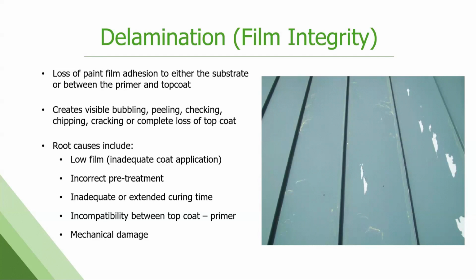I've listed the most common ones we see, which is low film. That's a coater application issue. Bad pre-treatment, you'll get loss of adhesion to the metal. Inadequate or extended cure time. So when we cure and dry these paints on the line, if we overbake it or underbake it, you might have film integrity issues out in the field. An incompatibility between your top coat and your primer can result in this.